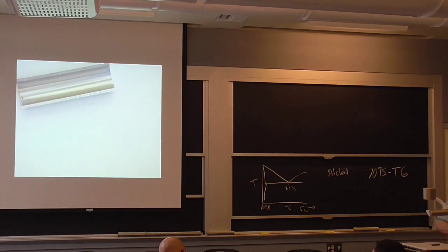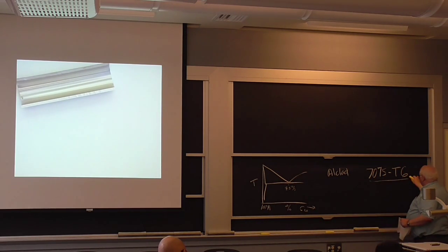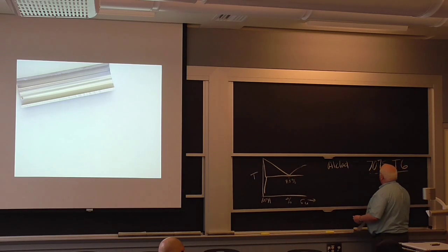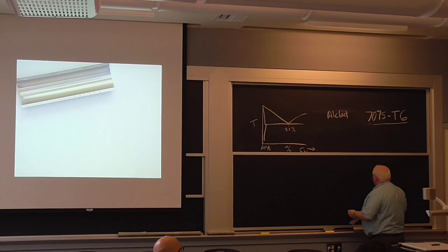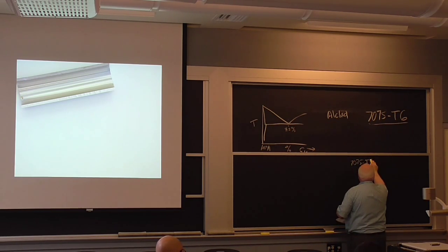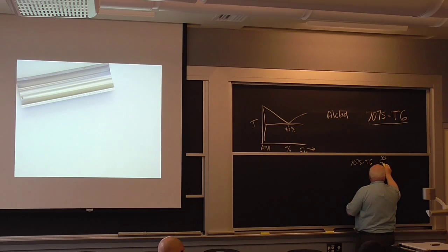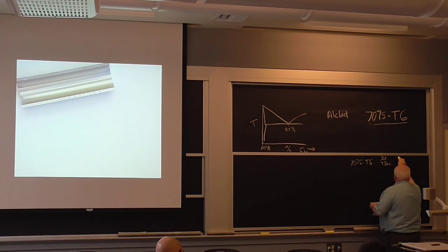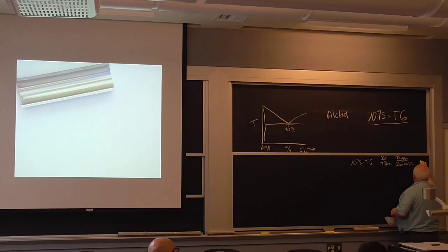This is part of a hydraulic cylinder that fractured. So this is 2002, Steve came to me, here's the letter from him. It was 7075 T6 alloy that they were using, which had a yield strength of 73 KSI, really high strength aluminum, had a toughness of 26 KSI square root of an inch, and had a wall thickness of 1/8 of an inch.